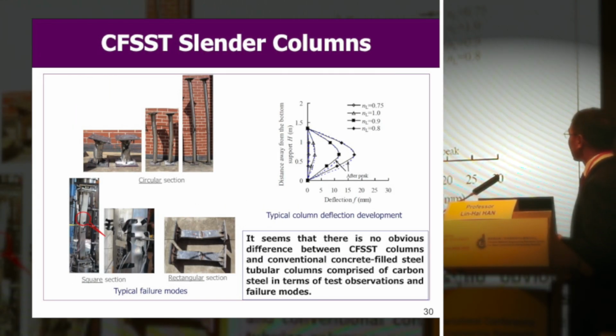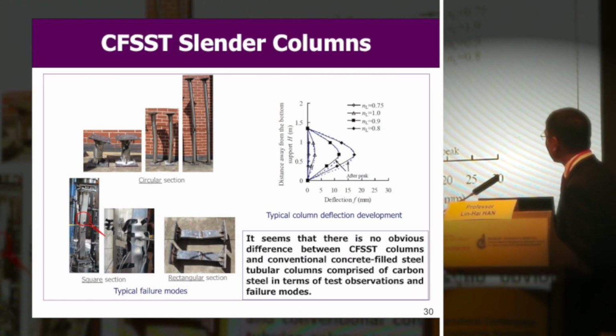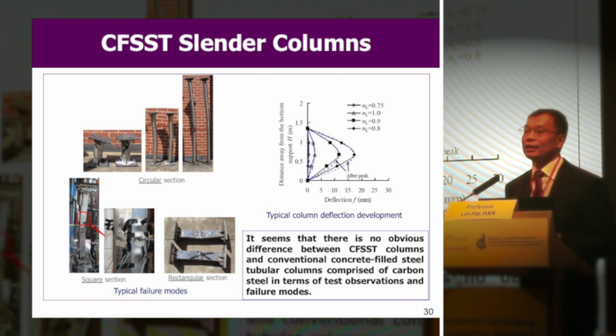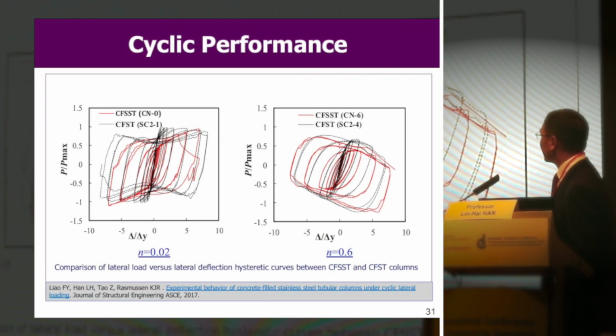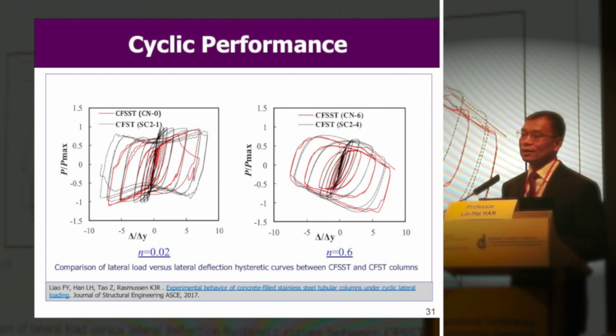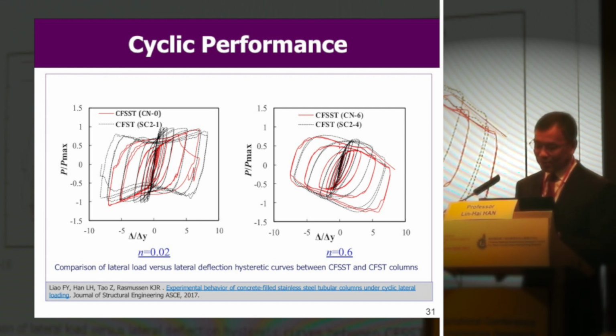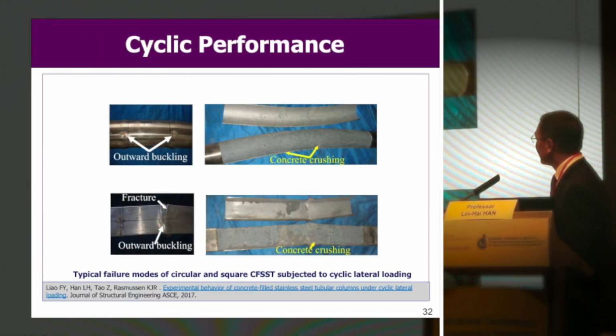This is for long column. The long column's behavior is quite similar to that of the corresponding concrete filled carbon steel tube, cylinder column. And cyclic performance is quite similar. You can see CFST is that line, solid is CFSST, quite similar. So quite a similar response, though the bond strength between the steel tube and the core concrete is different.